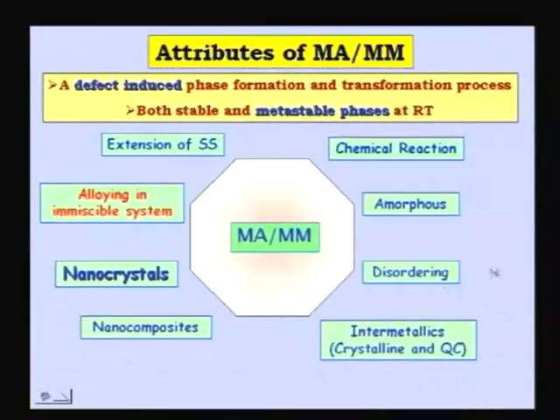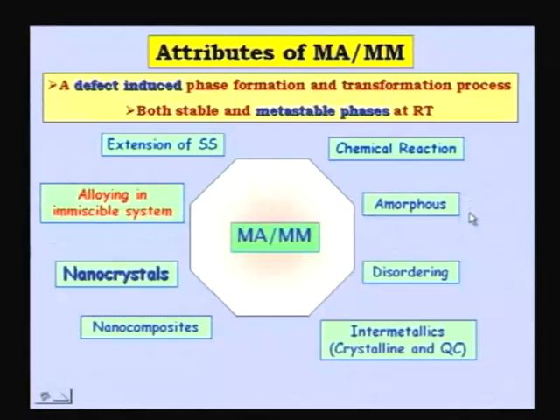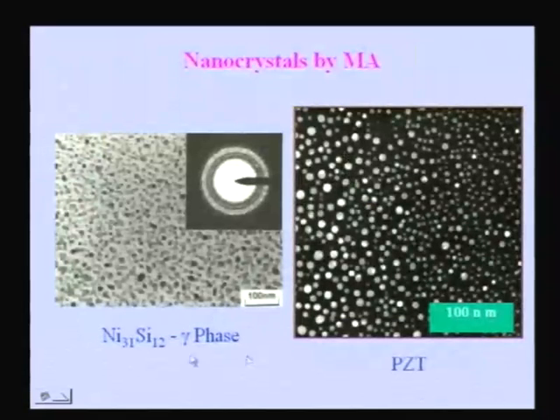Then one can have disordering. Before that I should say, one can make intermetallics after alloying. After solid solution formation, the next possibility is intermetallics. One can make intermetallics, whether they are crystalline intermetallics or quasi-crystalline intermetallics. We have talked about this at some stage when we talked of nanocrystalline materials. One can have disordering in the intermetallics. One can take an ordered intermetallic and make it disordered. I told you why we want to make it disordered: because a disordered compound is more ductile. So if you want to introduce some ductility into a compound, you can take an ordered compound and put it into a ball mill, make it disordered, and even make it completely amorphous, and one can also introduce chemical reactions. So these are all things one can do, and these are some of the examples.